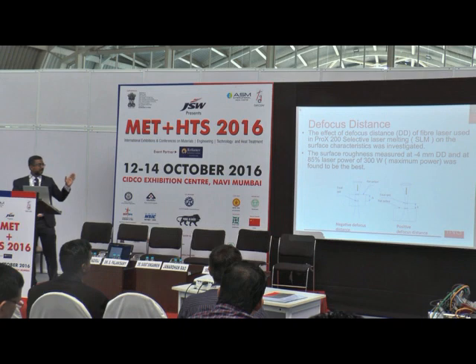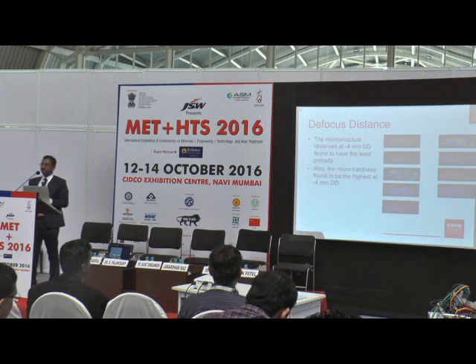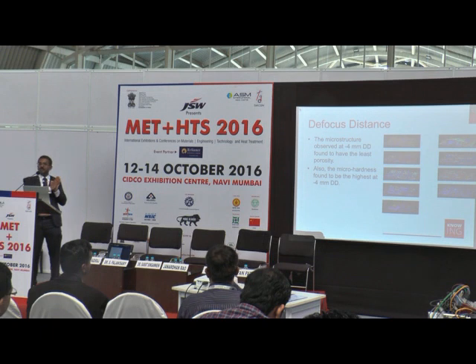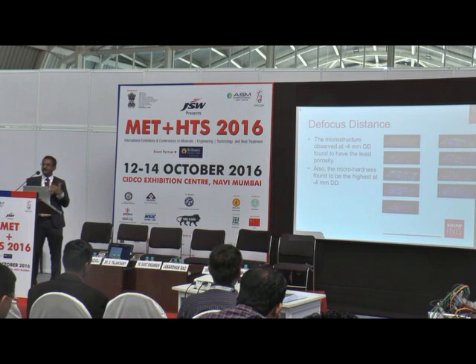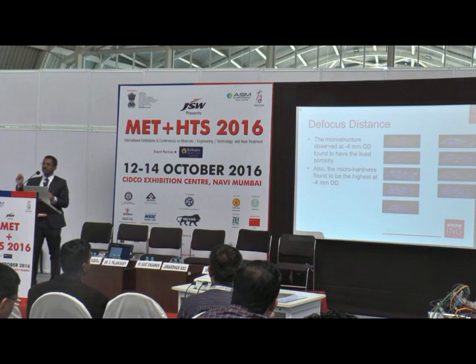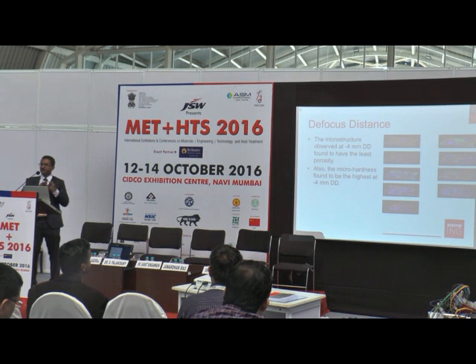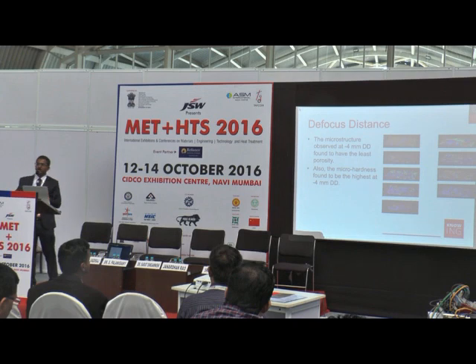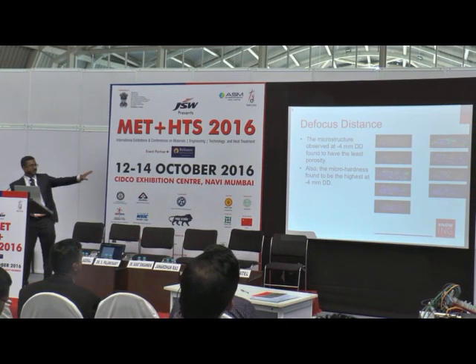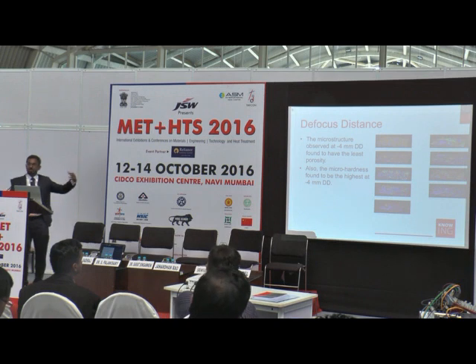That will determine. We had trouble with recycled powder. When you have fresh powder and use -4 defocal length, all perfect. But when you recycle the powder quite often, then you have to change the parameters. So that's where the challenge is. When do you change that particular parameter? And you're changing the properties of the component, which is very hard to know. That's why quite a lot of research is happening in this area, mainly trying to optimize those conditions so that you can achieve consistent properties along the component. This image just shows the surface roughness values which we tried to measure on a component.